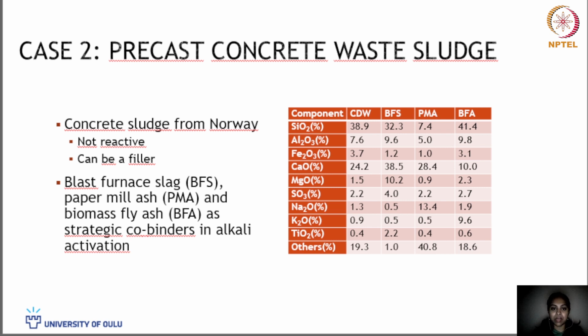So in this experimentation, we tried to use different co-binders in a synergy that would help us produce alkali activated granules, which is why we wanted to supply some silica, alumina, and also some of the activators. So we used blast furnace slag, paper mill ash, and biomass fly ash, which are local industrial side streams, as a strategy to produce co-binders for alkali activation. You see these are added in different percentages here for this study.